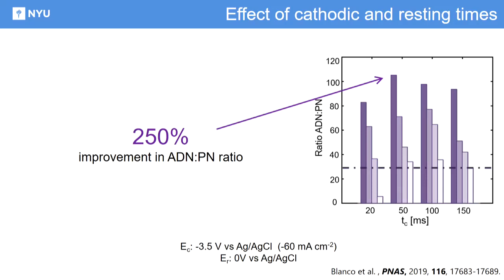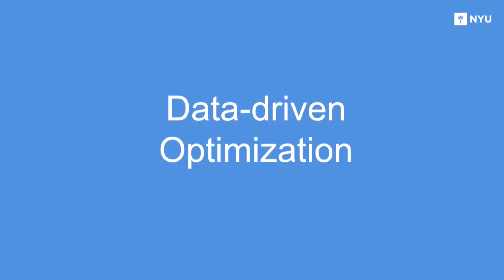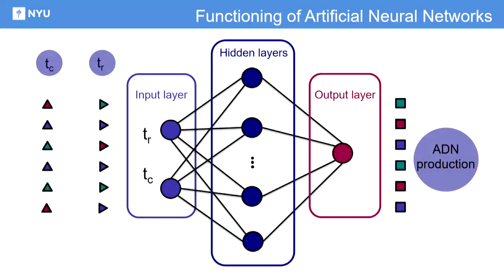So we did a lot of continuum modeling trying to understand what's happening at the interface, but it's kind of complex. It gets you to a window of times that are relevant. And here's where I think data can really help, because we can learn from what the experiments are telling us, and then just by using regression models like artificial neural networks, we can develop predictive tools for the production rate of the molecules that we want, adiponitrile, based on some of the parameters that we had identified that had a high effect. In this case, cathodic and resting times. And the way that this looks is that we take the data, we train the networks, and then we can generate predictive tools that allow us to go to conditions in which we can optimize the process.